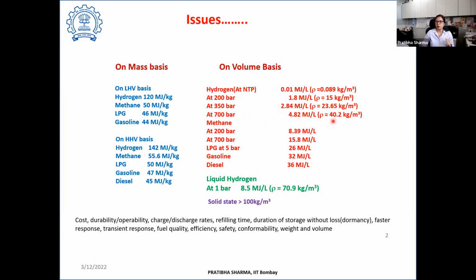Another way to make it more dense is to liquefy it. Under 1 bar pressure, if we liquefy it and convert it into liquid hydrogen, the density improves to 70.9 kg per cubic meter, or per liter we can store 8.5 megajoule of energy. Now this seems to be quite reasonable. As we compare with gasoline or diesel, this is about one fourth that of gasoline.